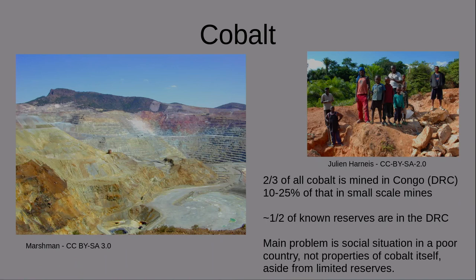Cobalt. Cobalt is a huge problem. A problem, for one thing, because we don't have too much of it. As you have seen, it's about as much as lithium. And you need a lot more cobalt in your battery than you need of lithium, simply because, I mean, it's the same number of atoms. If you had lithium cobalt oxide, you need one lithium atom and you need one cobalt atom. But the problem is a cobalt atom is about 10 times as heavy as a lithium atom. So you need a lot more cobalt than you need lithium.